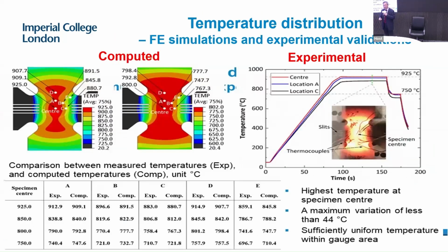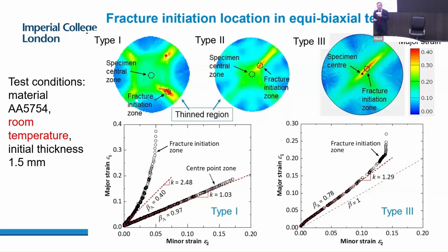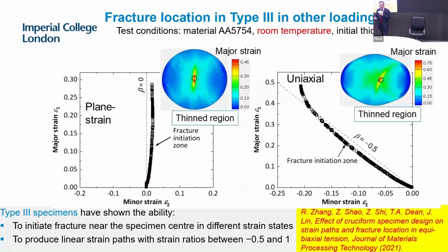Firstly, we look at temperatures, how to heat the materials, because for this kind of specimen with non-regular geometries it is very difficult to heat. We developed a way to heat this and checked the temperatures at different locations. Then we look at the failure when we stretch the material. What are the strains for type 1, type 2, type 3? We can see for type 3, the failure occurs almost near the center of the specimen, and type 1 is a bit away from this.